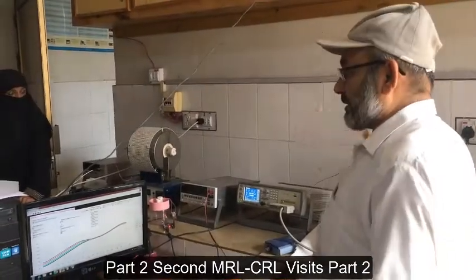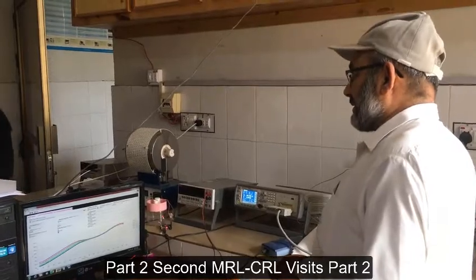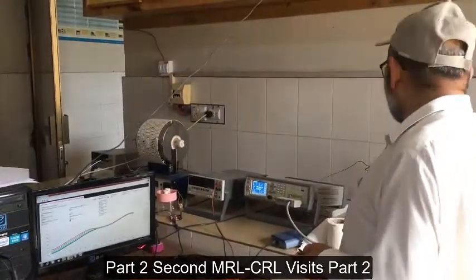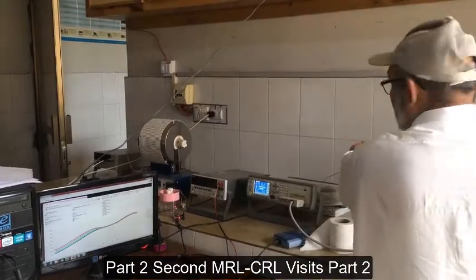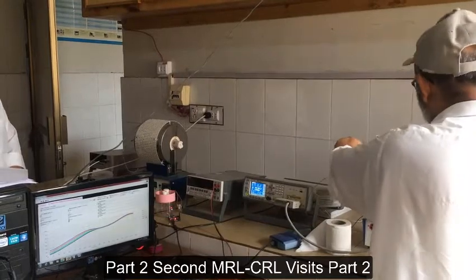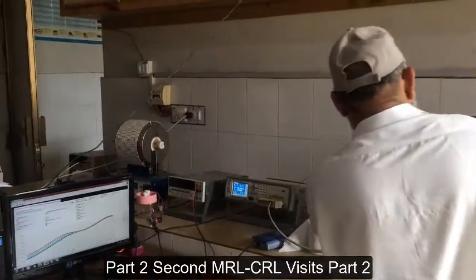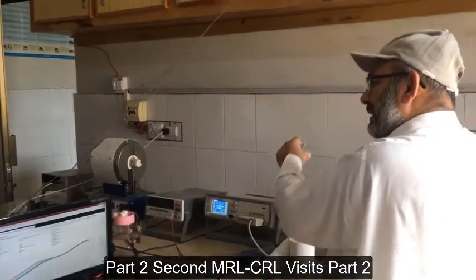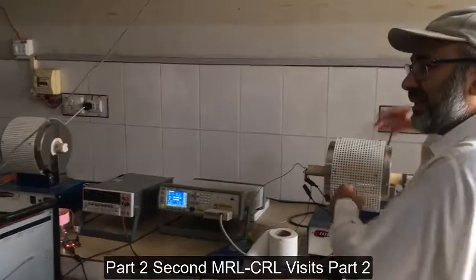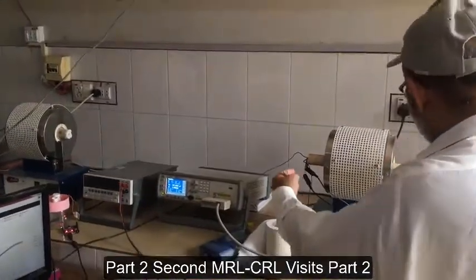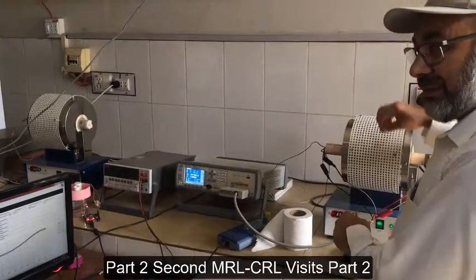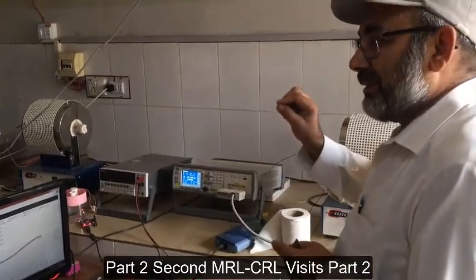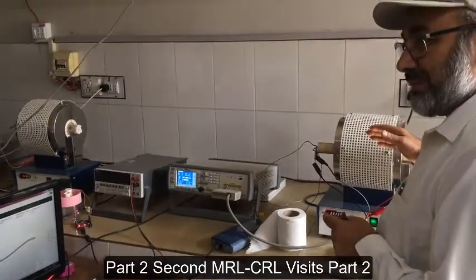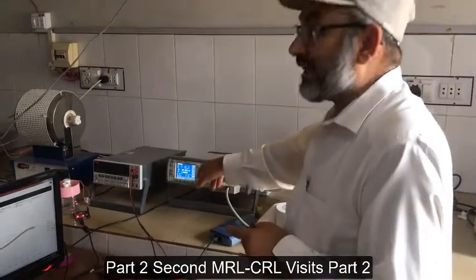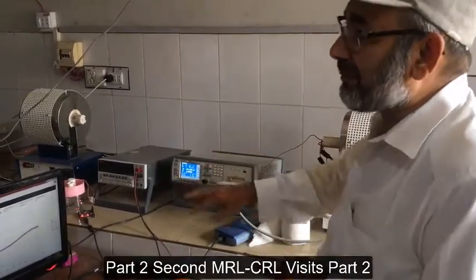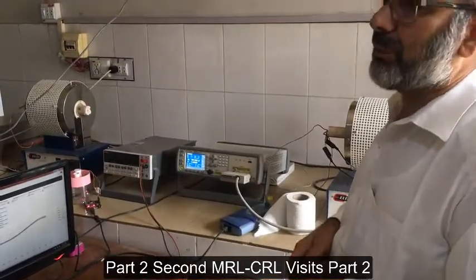These two furnaces you see are ordinary tube furnaces from Elite Furnaces UK, and an alumina tube is passed through it. The sample is connected through platinum wires, because platinum wires do not melt up to 1000 or so degrees centigrade. So platinum electrodes are used. The sample is in the middle, and a thermocouple is near the sample. So we measure the change in temperature and the associated change in capacitance. And then the capacitance measures the dielectric constant, which you call the relative permittivity of the material.